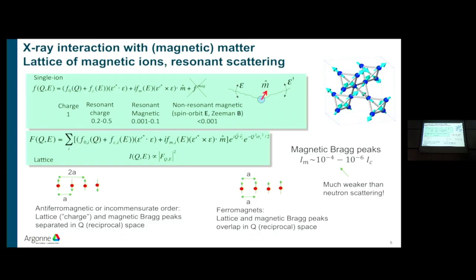So when you square such a small quantity, you get magnetic Bragg peaks that are much weaker than what you measure in neutrons, maybe 6 orders of magnitude or more. Now, when you're looking at antiferromagnets, where the magnetic periodicity is different than the lattice periodicity, you would think, okay, maybe I have some hope because the magnetic peaks will be separated in reciprocal space from the lattice peaks. And even though they are small, I can measure them. When I have a ferromagnet where the periodicity is the same as that of the lattice, the magnetic peaks are on top of the charge peaks, and there's no way you can measure 1 part per million easily.